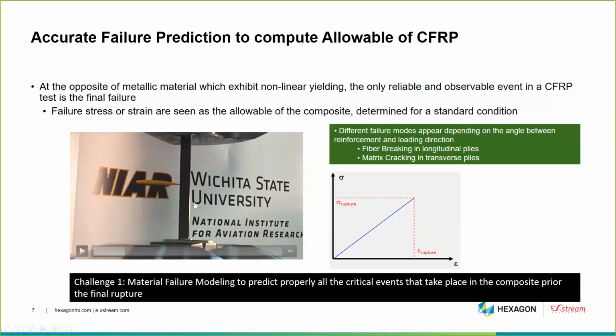And when we load a coupon like this, we can observe a very brittle failure, but between the moment we start to load the coupon up to the final failure, some critical events take place on the coupon, such as initiation of matrix cracking and initiation of fiber breaking. And if we want to be able to predict the final failure, we have to use a numerical model that is able to predict all the critical events that take place prior to the final failure. So that's the first challenge: to develop or to use a material model that will be able to predict properly all the critical events that take place in the composite or in the coupon before the final failure.